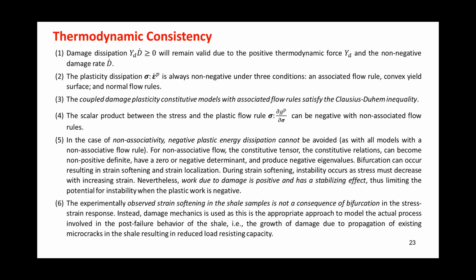Okay, so for a non-associated flow rule, again, we can have negative plastic energy. The important thing here is that damage added to the plastic has a stabilizing effect because damage always produces positive energy dissipation. So it stabilizes any negative plastic energy dissipation from the non-associative rule. We note here that although we have a non-associated flow rule, we are not invoking bifurcation or strain localization as the reason for the strain softening. Again, the strain softening is a result of the damage of the material due to the initiation of the fracture and the propagation of the fracture during shearing.